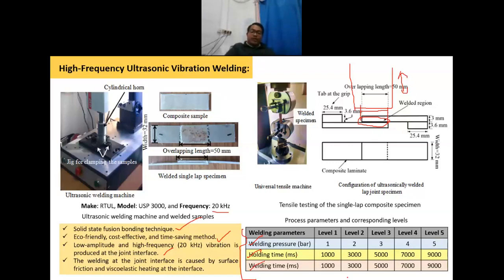All these parameters are very important. For example, if welding pressure is very high, what happens? Your horn is vibrating, so at the joint interface temperature will generate and it will melt the polymer. After that you have to apply pressure, which is called the welding pressure. That means the horn will stop vibrating and it will apply the pressure. If this pressure is very high or very low, it will have a detrimental effect on the joint strength, because if it is very high, my melted polymer will squeeze out from the overlapping area. And if it is very low, there will be no adequate bonding between the two specimens. So it should not be very high, it should not be very low.